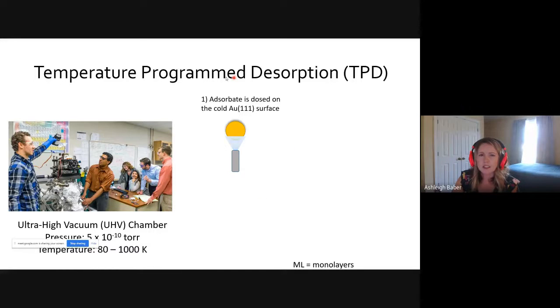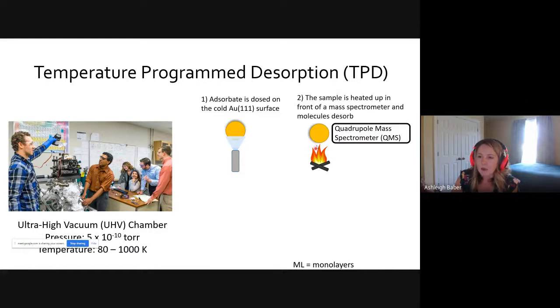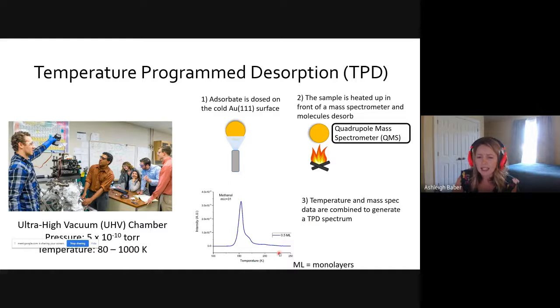And I just wanted to talk about TPD very quickly, temperature program desorption, where we have a metal surface of interest. Here, this gold disc represents a gold 111 surface, and we cool it down and spray some molecules on it. And when we heat it back up, those molecules come off, and we can monitor them using quadrupole mass spectrometry. And if it's an inert surface like gold 111, then if we put something like ethanol down on the surface, then we see that ethanol comes back off of the surface. And we see a plot like this.